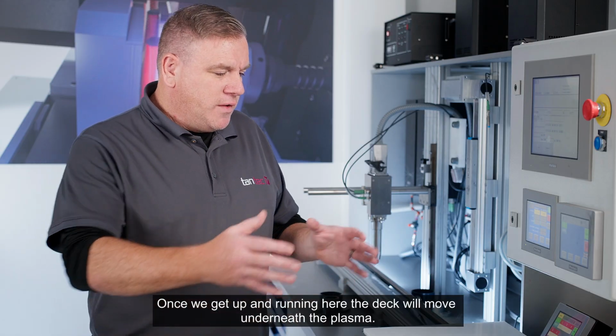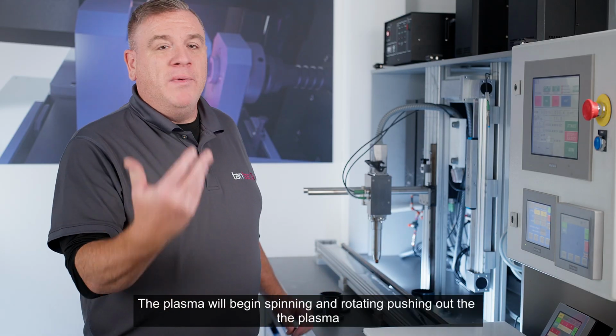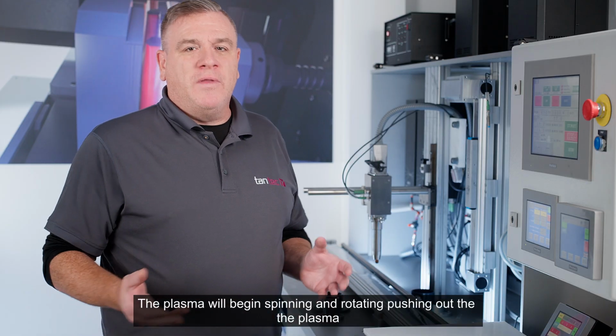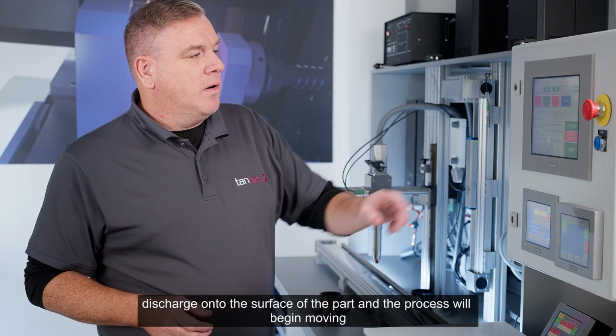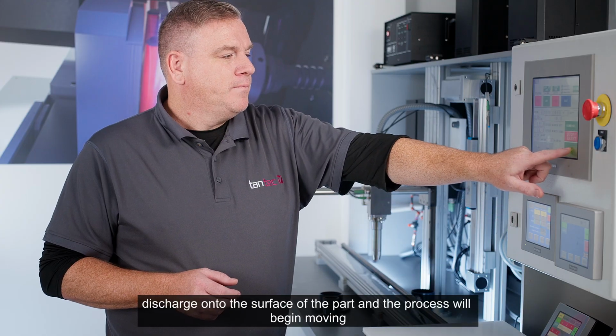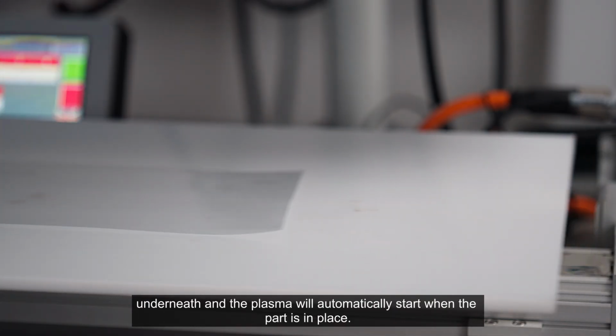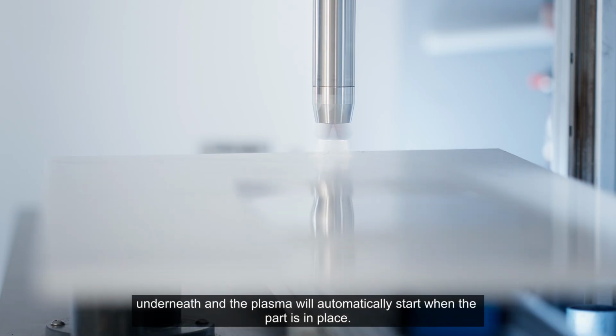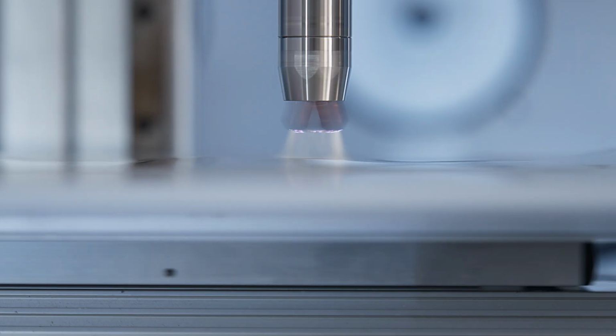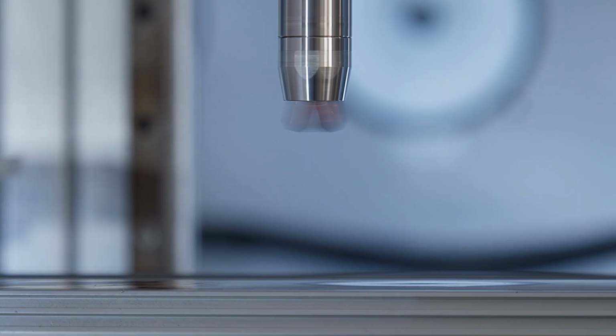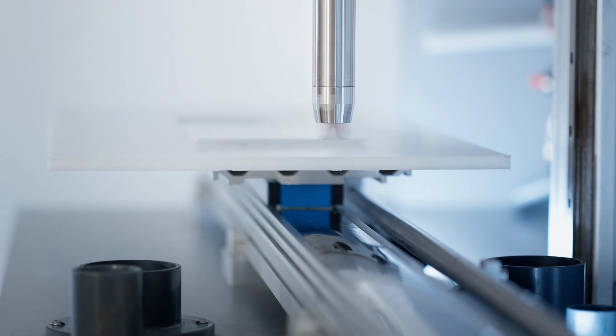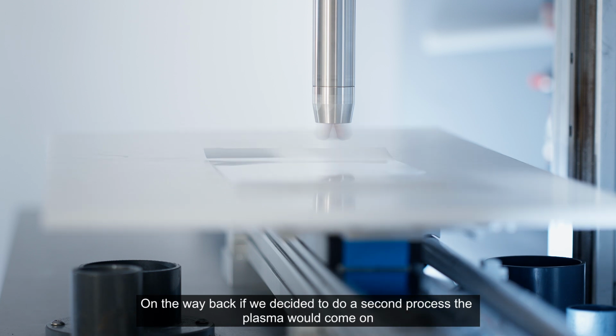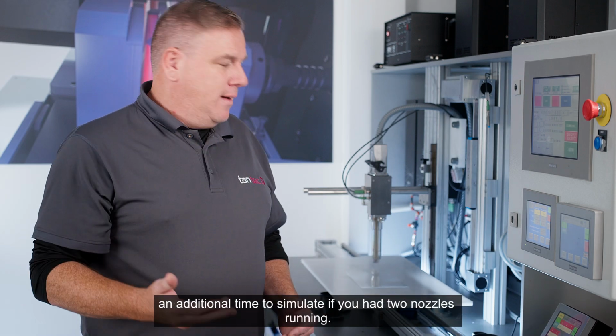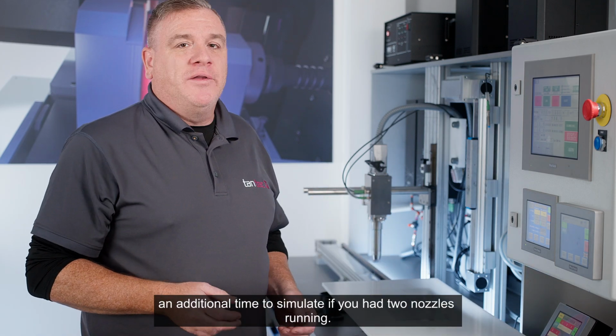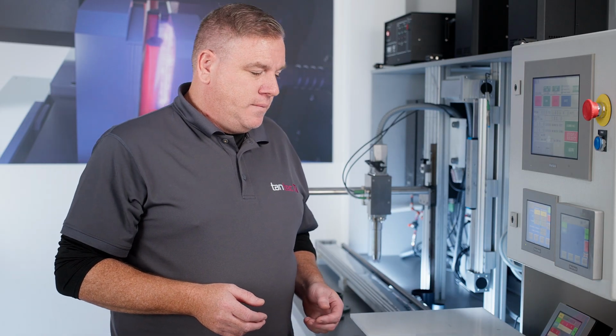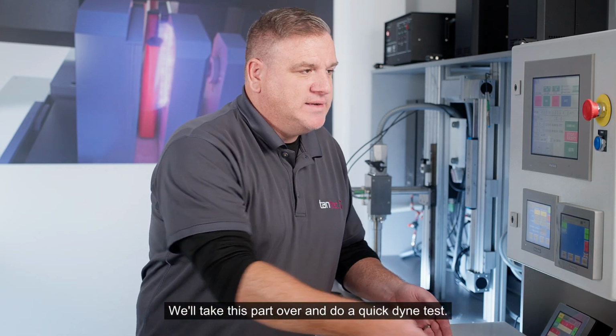Once we get up and running here, the deck will move underneath the plasma. The plasma will begin spinning and rotating, pushing out the plasma discharge onto the surface of the part. And the process will begin moving underneath, and the plasma will automatically start when the part is in place. On the way back, if we decided to do a second process, the plasma would come on an additional time to simulate if you had two nozzles running. We'll take this part over and do a quick dyne test.